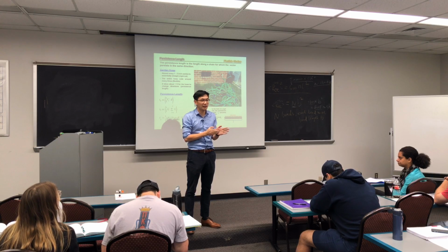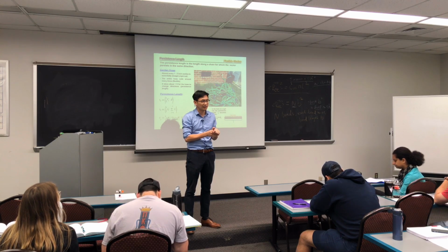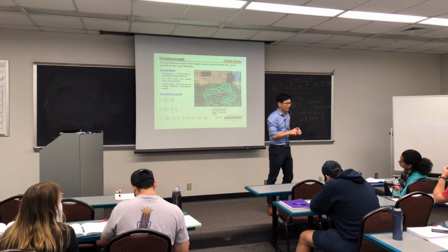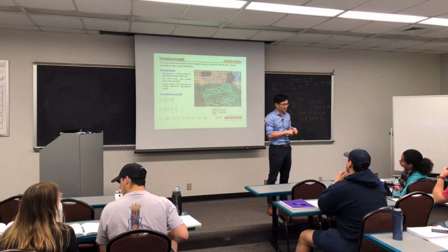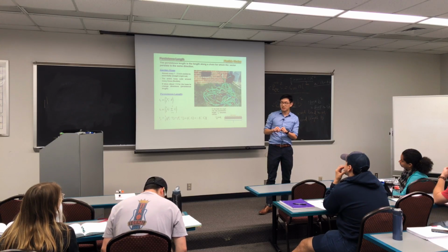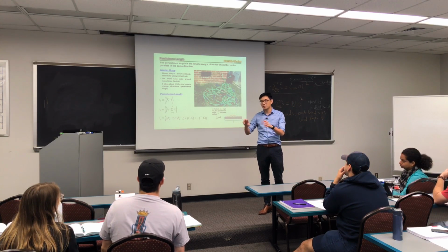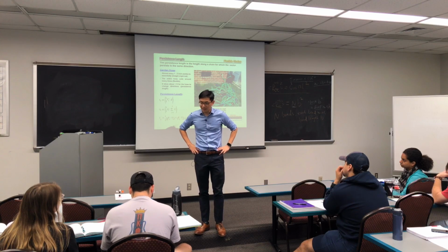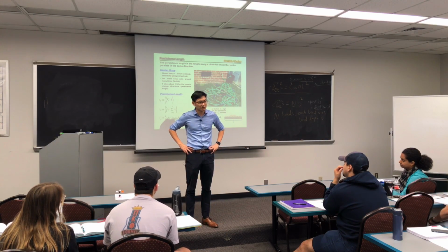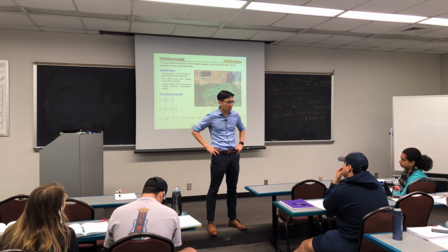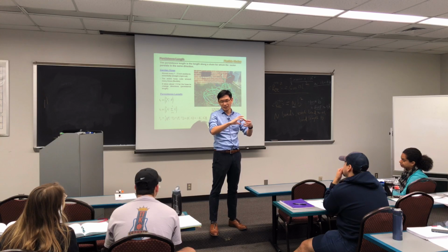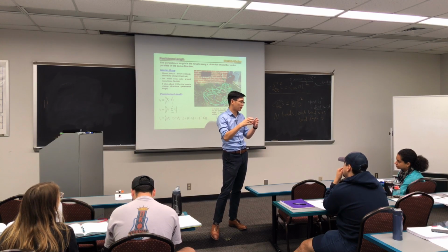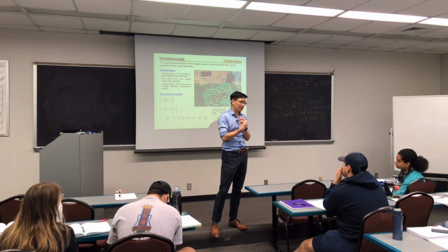An example would be the DNA molecule. DNA has a persistence length of about 200 to 300 nanometers. What that means is DNA is very rigid in the double helix form. It doesn't like to be bent or play around. Intermediate is conjugated polymer, a class of polymer I study in my group, which has a lot of aromatic rings in the polymer backbone. Between the rings you can have bond rotation, but around the bond you don't have much rotation and ability to change.